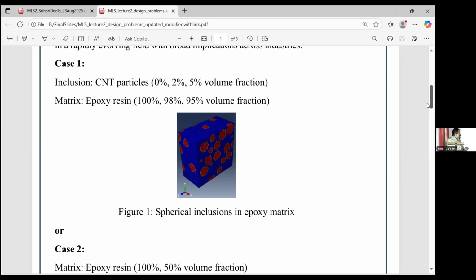stiffness value. Now for the second simulation, you can add 2% volume fraction, and then see whether the strength you got for the pure epoxy case is increasing or not. Now you have added inclusions, so there is a kind of interface effect. The properties have to increase. When 2% is spherical inclusion, the remaining 98% should be the epoxy matrix. The next one is increasing further to 5% volume fraction of spherical inclusions and the remaining 95% matrix. In this case, is the strength further increasing or not? This is the kind of analysis you have to do in the first problem.